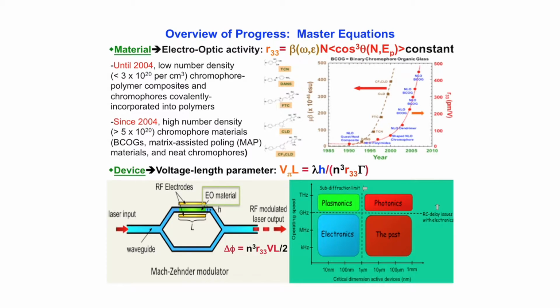Now, you would note that this critical figure of merit for devices relates inversely to the electro-optic activity. So the bigger the electro-optic activity, the smaller V pi L. It also relates to the separation between the drive electrodes. And we might also note in passing that electro-optic activity induced by poling also relates to the separation of the poling electrodes, which are one and the same here.